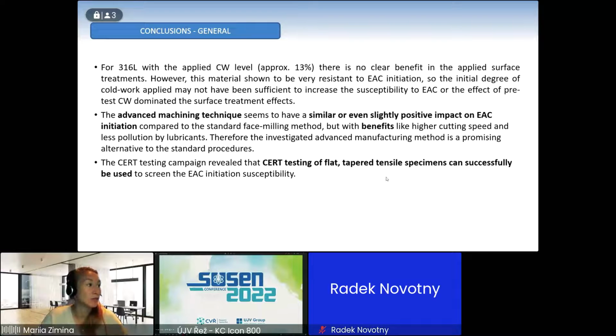Those were the testing results, and I would also like to mention the general conclusions which we observed during the whole project. So for the 316L with the applied cold work level, which is 13% in our case, there is clearly no benefit in the applied surface treatment. However, this material is shown to be very resistant to EAC initiation, so the initial degree of cold work applied may not have been sufficient to increase the susceptibility to EAC, although we couldn't introduce more cold work because we wanted to simulate the real conditions in the power plants, and this is the first point.